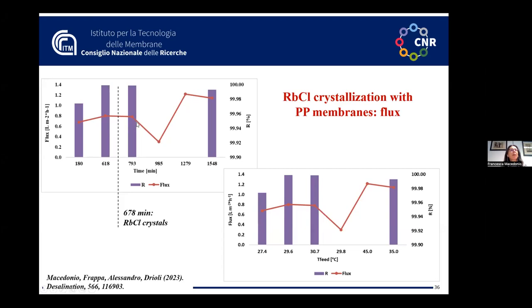After this, we have a strong decrease of flux, due to the very high concentration in the plant and due to the fact that we have a lot of rubidium chloride crystals circulating in the plant. Therefore, after around 1,000 minutes from the start of the test, we have to stop the test, filter the feed solution, remove all the rubidium chloride crystals, and then re-put the filtered feed solution in the plant to try to continue the process to check if more rubidium chloride crystals can be achieved.